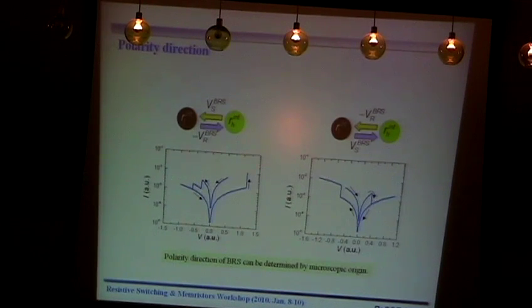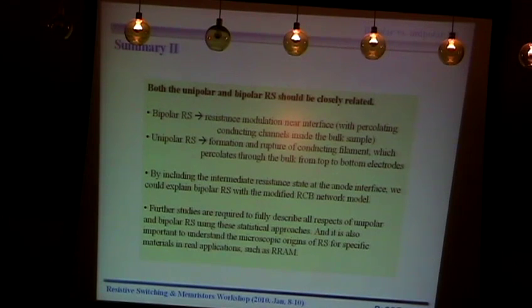And also, many people reported the polarity direction changing. So in here, original simulation has been done in here with this kind of polarity changing. But if you change this polarity direction, then you can actually see that polarity direction becomes reversed. It's just been observed by many workers. So this model, a very simple model, can describe the many aspects of this bipolar switching as well. So this is a brief summary.